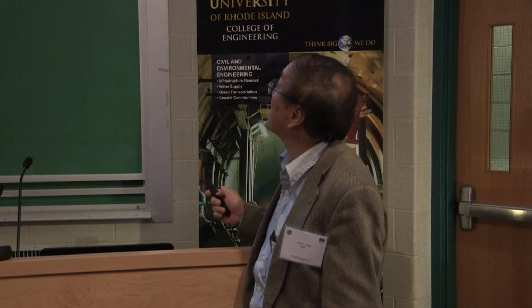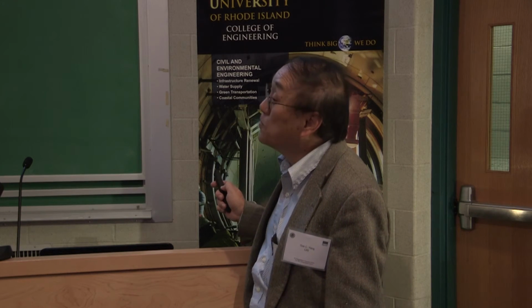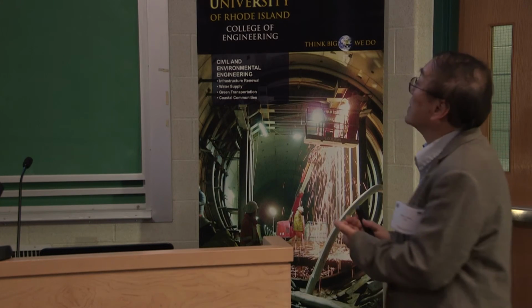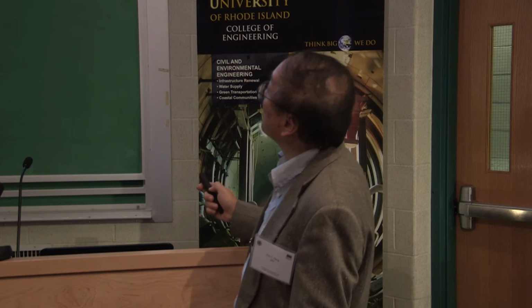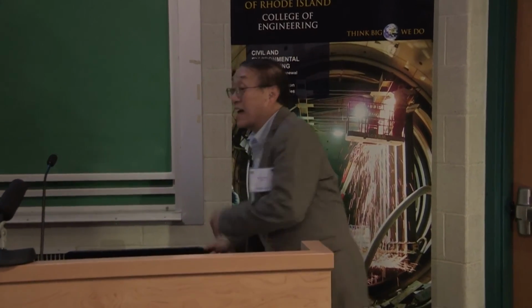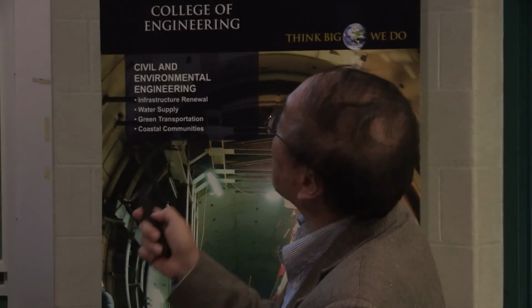So our question is, could we use the contact angle to predict which paint and which surface are a good match? Intuitively, we think this is better wetting and this is not so good. Is there a quantitative correlation we can rely on? We are running out of time, so let me go to the contact angle measurement equipment, and these are some of the contact angles. We collected hundreds of test cases, and what is interesting is the correlation.